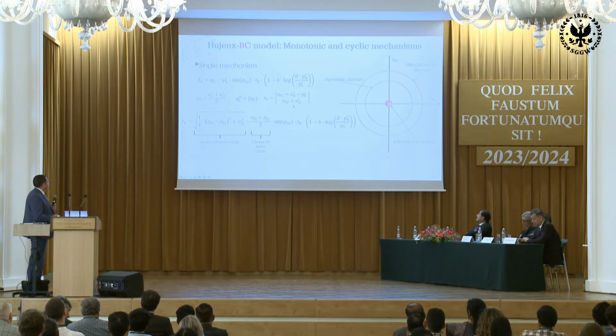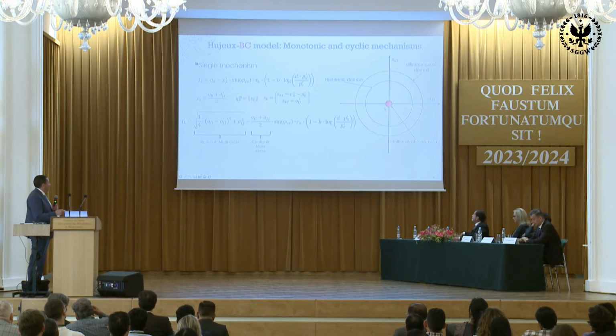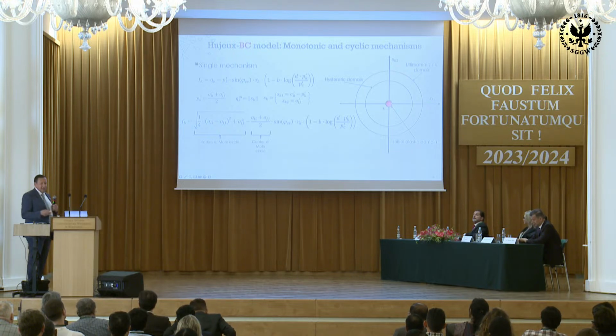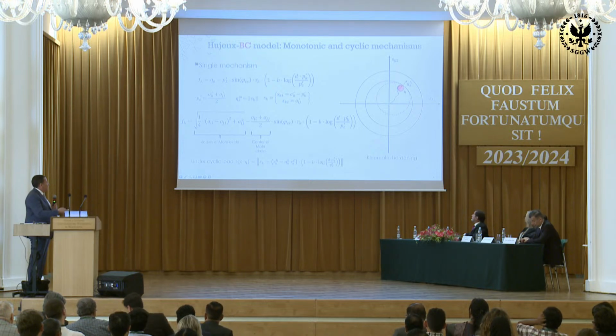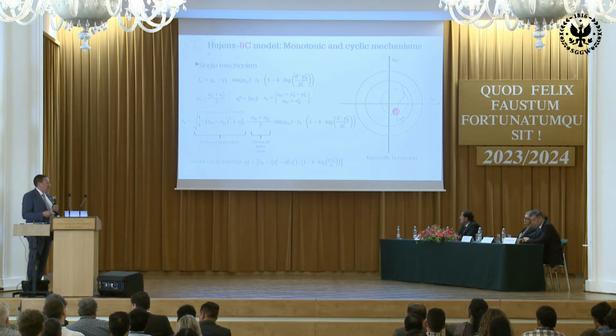So what does it mean? Now I write the same equation that I was showing before. We write it in a different mathematical form that allows us to normalize things and to have it in terms of circles. In one of the mechanisms, this would be our elastic domain, and then when you load your material, you have a hysteretic domain, and when you unload it, you have plasticity in unloading. This is what we call kinematic hardening. So this is the motivation for us in using a model with kinematic hardening.